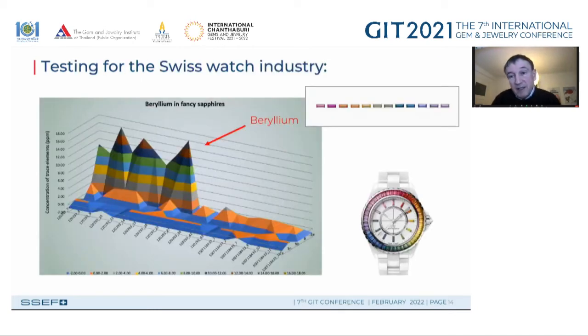This is just to show you the challenge. We at SSEF work closely also with the Swiss watch industry, and here we talk about very tiny stones, millimeter size. And the question is, what has happened to these stones? Are they natural, synthetic? Is there some treatment applied to these stones? What we have here is a series of samples, and the mountain range you see in the background is the beryllium concentration present in these stones. And these stones, in fact, have been diffusion treated by beryllium.